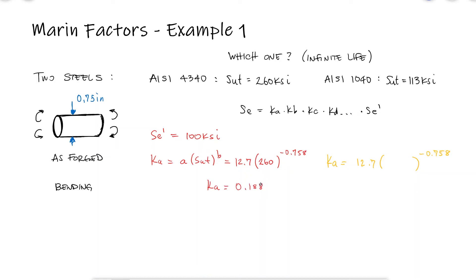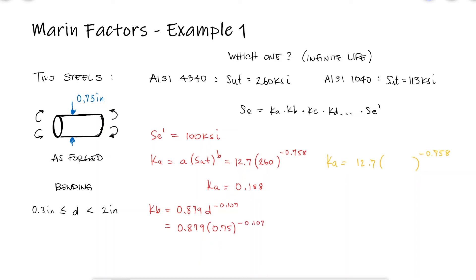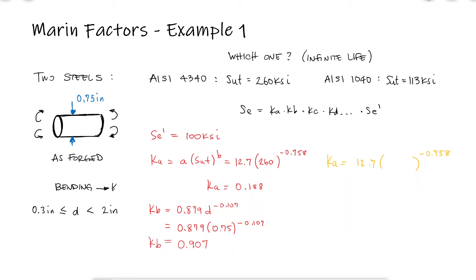The size factor Kb uses the expression for diameters between 0.3 and 2 inches. With an effective diameter of 0.75 inches, we find a size factor of 0.907. Since bending is the type of loading, the loading factor Kc equals 1. There is no mention of temperature or reliability, so we assume Kd and Ke to be 1.